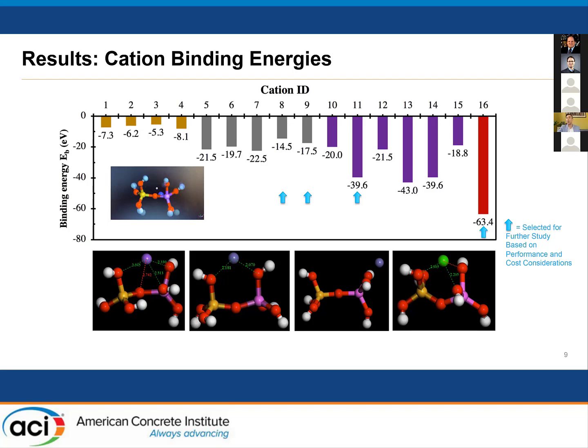So I'm showing you here this inset. Sorry, the video won't be able to play because this is a PDF, but this blue dot here is really sodium. So this is typically sodium in regular geopolymers, which can, upon exposure to sulfuric acid, be ejected due to the hydronium ions that are entering the system due to the acid attack. And we can also get ejection of the aluminum if the sodium leaves the system as well.